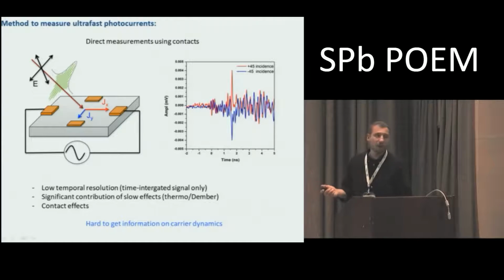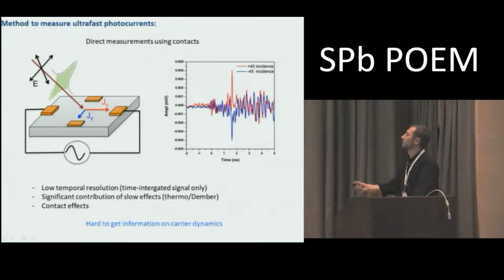Okay, so how to detect these currents? The simplest method is just to apply conductive electrodes and to measure the photocurrent directly by measuring the voltage drop across these contacts by using an oscilloscope or some other ammeter or voltmeter. However, these methods have low temporal resolution and provide only a time-integrated signal. These measurements are very sensitive to slow effects, and also by applying additional contacts to the sample, we induce, for example, band bending around the contact area or some other contact effect. So again, this is not good to get information on carrier dynamics.